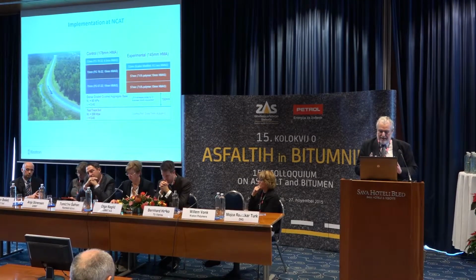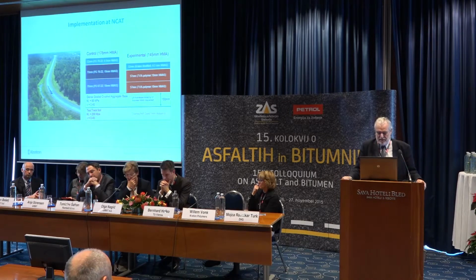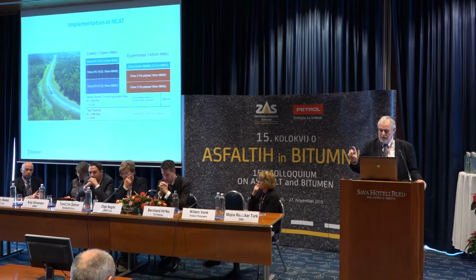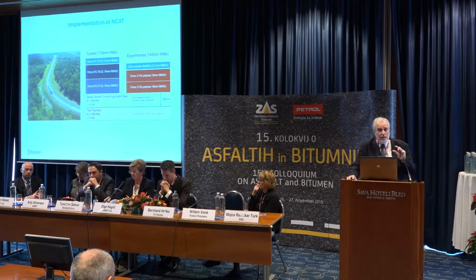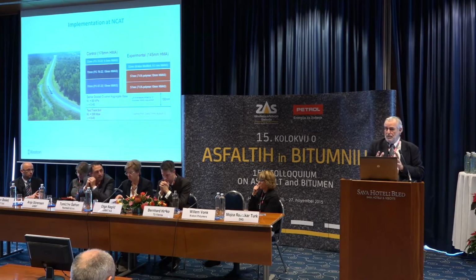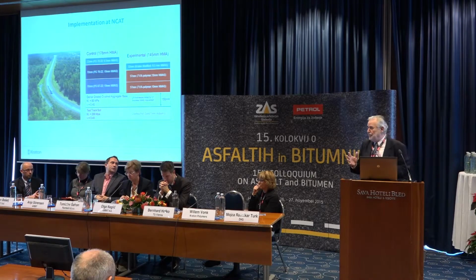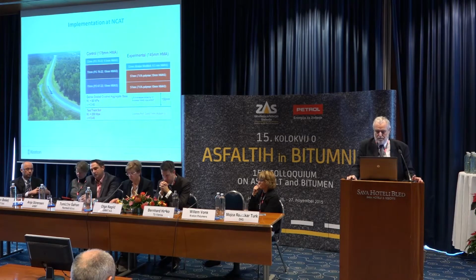What we did was we had a control and a highly modified layer. As you can see, the control was already with PMBs in the 2 top layers. The highly modified section was completely with highly modified, and it had a thinner layer. We were not allowed to go even thinner than that, because if you disrupt the system by a complete failure, then obviously they have to repair, and that gives an interruption of the total testing sequence.